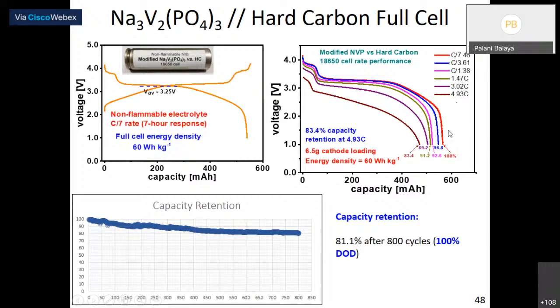Here I am showing you different C rate performances. This is the low C rate. This is the high C rate. You see here, I can discharge close to about 5C. 5C is typically about 12 minutes per charging, per discharging. I can still retain 83% capacity as compared to low C rate. So very decent high C rate performance.